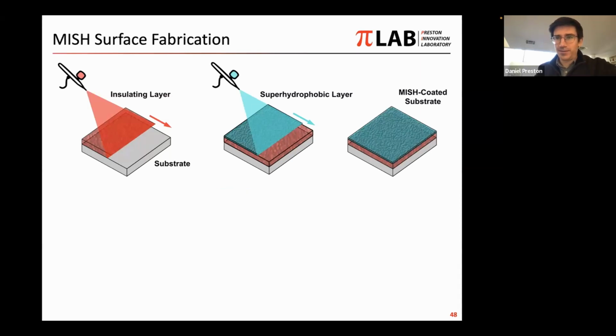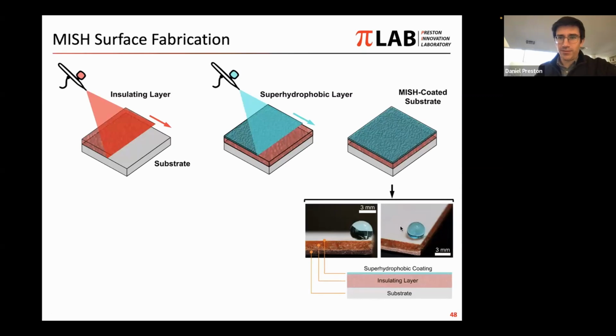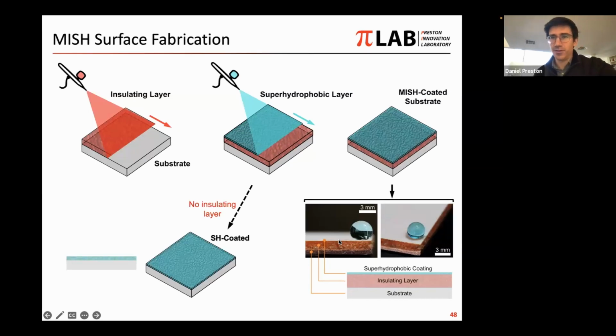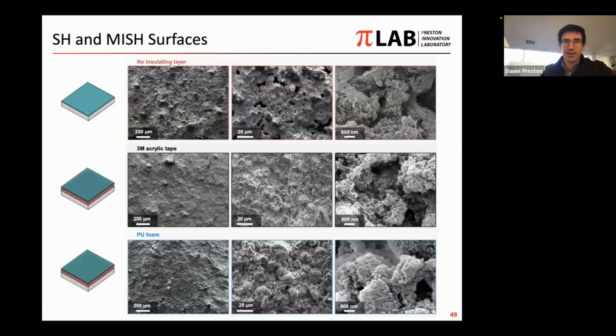In order to keep things quantitative, you saw the picture here of the layers in between. We have the insulating layer and the superhydrophobic layer. We also wanted to compare this to a baseline of a substrate that has been coated with just the spray-on superhydrophobic coating. And so that allows us to have this direct comparison to illustrate the effect of the insulating layer. We want to isolate that, right? And I show here a few images. These are SEM images. We're again trying to make sure we can isolate only the thermal effects and not the textural or chemical effects.